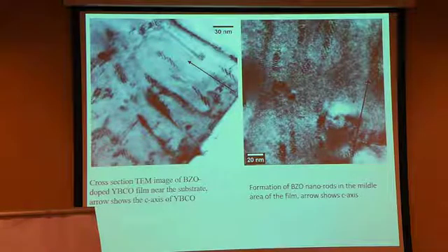If you have all the defects parallel, columnar defects, the vortices will form a Bose glass, and in a Bose glass, if you don't have any other type of defects, you will have a double kink formation, and because of the interaction between those two loops, the double kink will extend, and the vortex will move itself to another pinning center.